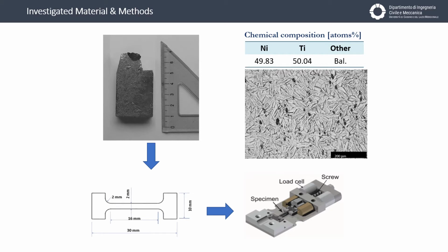It's a mini machine, a patented mini machine, which allows us to perform a loading test using a load cell in order to measure the total force applied on the specimen, and with an LVDT we can control the movement of the crosshead. This tool is able to put the specimen under load inside a machine able to perform the XRD test in order to observe the diffraction spectrum, which is the base to better understand the position of atoms, and in this case the structure, the microstructure.